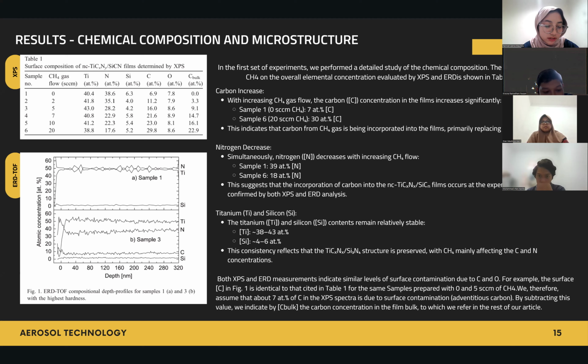And for figure 1 of the ERD-TOF, we can see that it has similar data to the XPS: in sample 1 there is no concentration of C, and from sample 3 onwards, as the samples increase, there is the presence of carbon, but the nitrogen is decreasing. So the XPS table and the ERD table are completely the same, but we assume that there is a 7% contamination in the XPS spectra due to adventitious carbon. So we value the C by subtracting the surface carbon concentration from the film bulk.